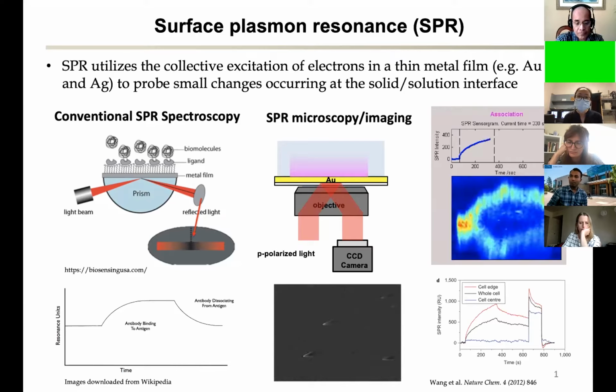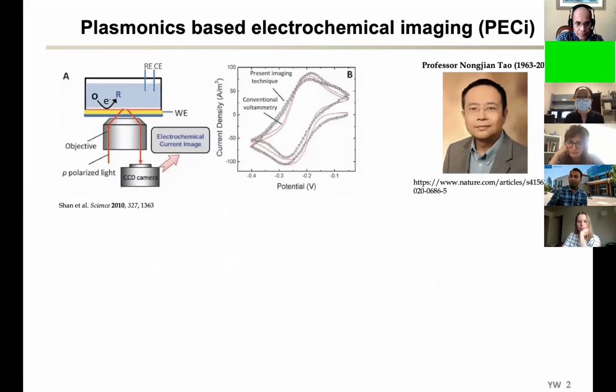And to add to that, SPR can also be combined with electrochemical measurement, and we call it plasmonics-based electrochemical imaging. This was first invented by the late Professor Nongjian Tao, who was also my postdoc PI. In 2010, they first reported this work using the SPR signal to measure the current in an electrochemical reaction. As you can see here, the signal from the SPR measurement fits the actual cyclic voltammetry obtained at the potential step very well.